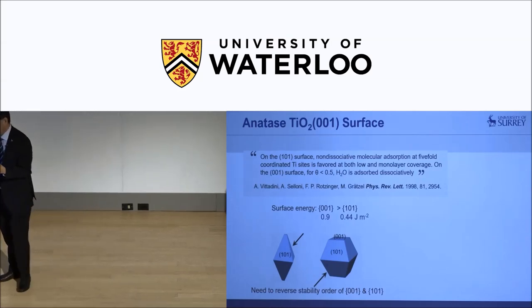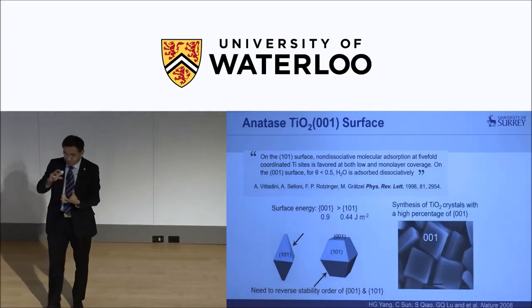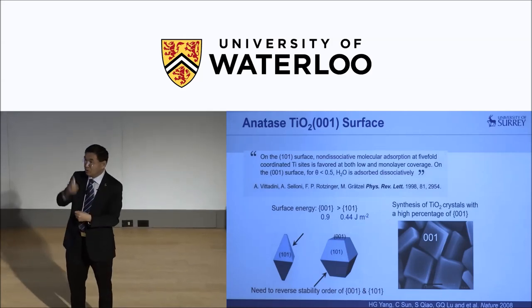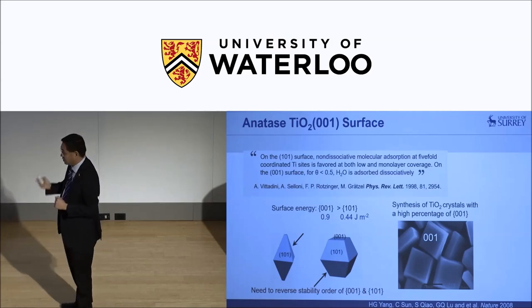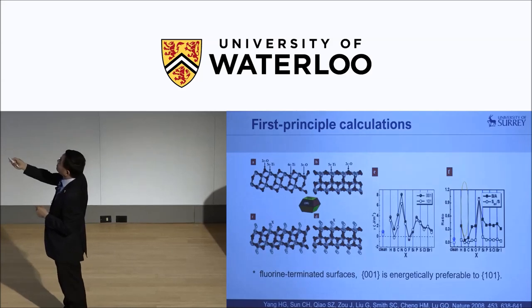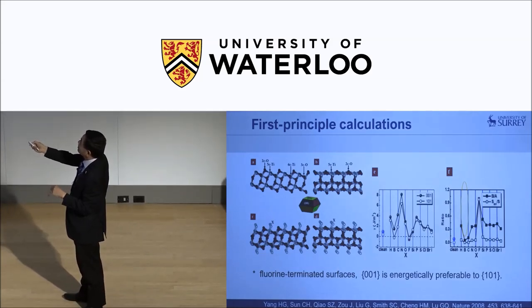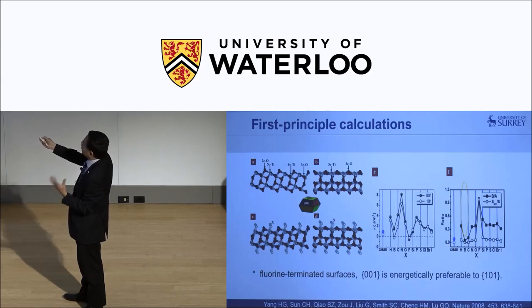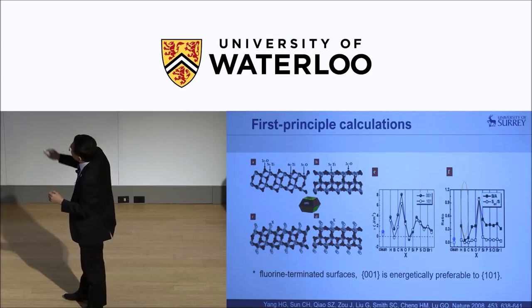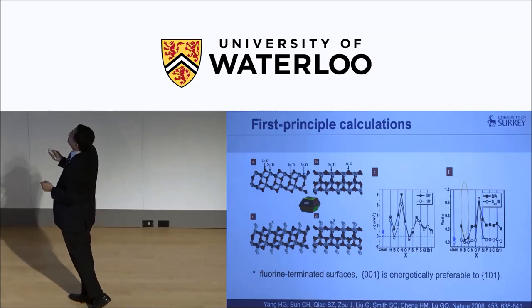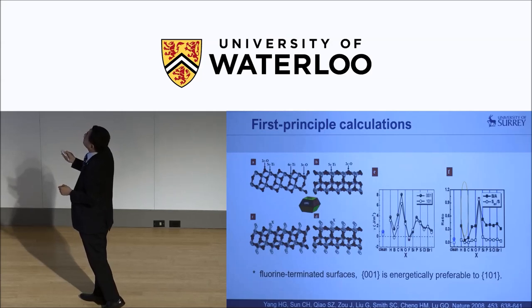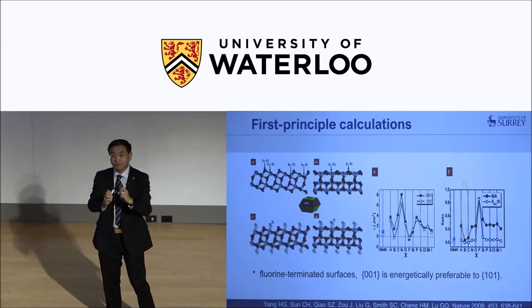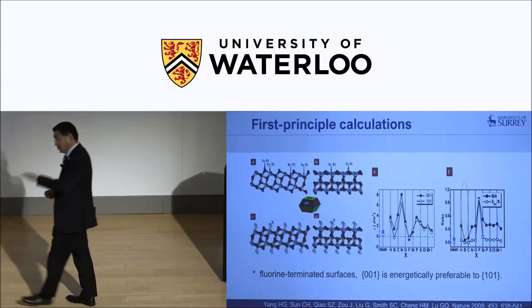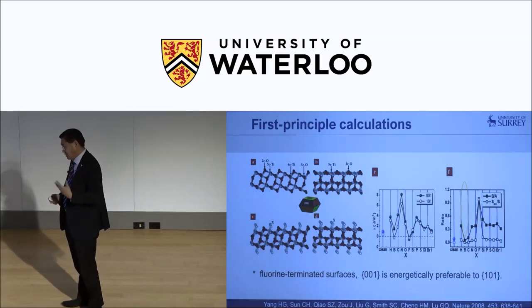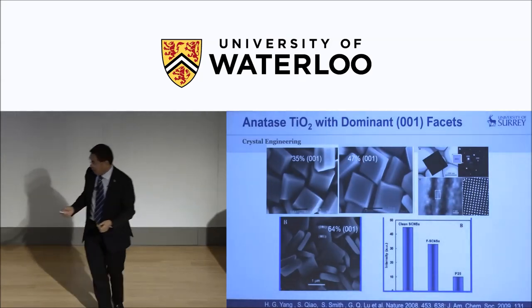And how to reverse the stability? Because high energy is not stable. And therefore, we have to think about how you are going to use capping agents or adsorbate to really reverse the stability. So we did a lot of quantum mechanical calculation. So this is unrelaxed. So 001 face is sort of half and half, 5 and 6 coordinate, and this is all 5 coordinated. That's the 101 face. And this is the adsorbate. And the adsorbate could be hydrogen, boron, carbon, nitrogen, sulfur, and so on. So the quantum mechanical calculation, ab initio simulation, tells us the lowest energy actually can be achieved when you put fluoride as X. The fluoride atom actually lowers the energy in such a way that it stabilizes this, and therefore the preferential growth happens.